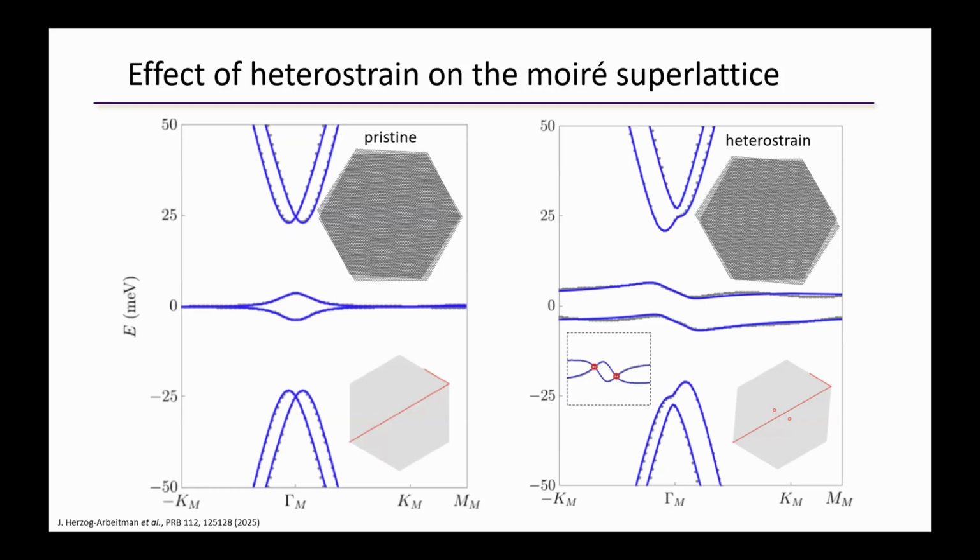There's an inherent topology that protects the Dirac crossings that's related to the C2 symmetry of the lattice, rotating by 180 degrees. Strain doesn't break that symmetry, so you need to maintain the Dirac points, but they often depin from the K and K prime corners and move towards the center of the Moiré-Brillouin zone. But in any case, what you can see is that in this cartoon lattice, I've just stretched one layer, and that really strongly deforms the geometry of the hexagonal Moiré pattern.